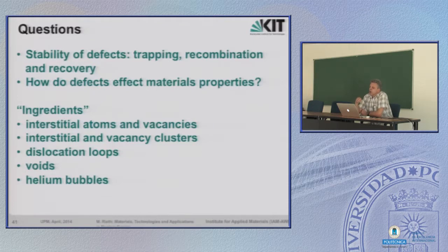And, as we have seen, there are a variety of ingredients to consider. We have the interstitial atoms and the vacancies, that's the point defects. Then we have interstitial and vacancy clusters, that's at least more than one or two of the Frenkel pairs. Then we have dislocation loops, which was also a specific kind. We have voids, and we have helium bubbles. And now, unfortunately, we have to go through all of these different varieties.